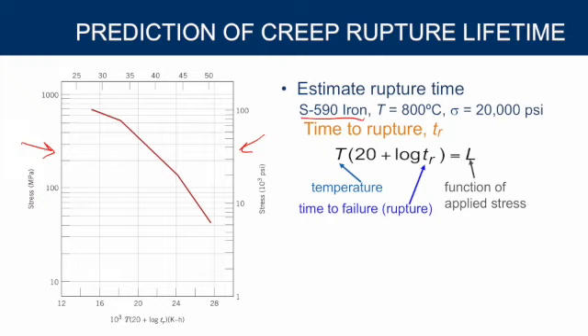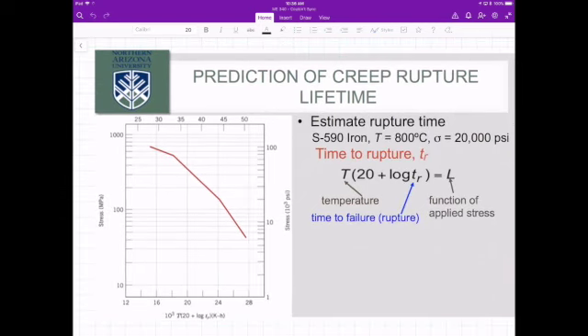And then on the x-axis, we have a constant, or an equation that solves for a constant, that is related to how long it takes for a material to rupture and its temperature. And if you look at this graph in particular, the temperature is in Kelvin and the time is in hours. Okay, so I have a question here. If we have a temperature of 800 degrees C and a stress of 20,000 psi, how long will it take to rupture? Okay, all right. So we have our prediction of creep.